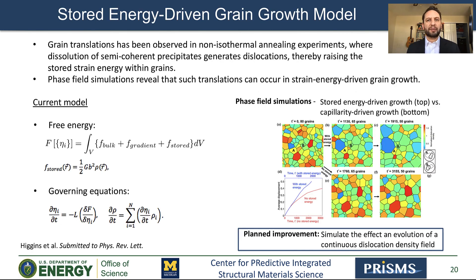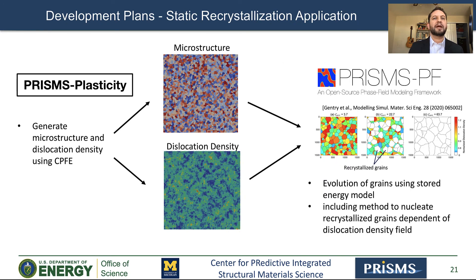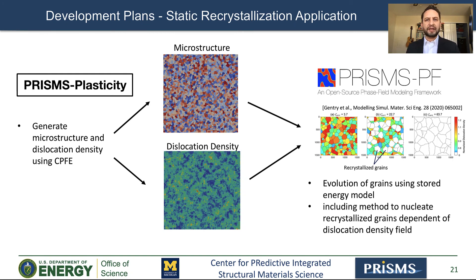Moving on to ongoing application development, we are working on a model to simulate grain growth with the effect of stored energy — specifically, grain growth under the effect of non-uniform dislocation density throughout the system, coupled with the evolution of the dislocation density itself. This model would then be applied to simulate static recrystallization. For this application, we will import grain microstructure and dislocation density maps obtained using crystal plasticity finite element in the PRISMS Plasticity application, and PRISMS-PF will then simulate nucleation and growth of recrystallized grains using this stored energy model.